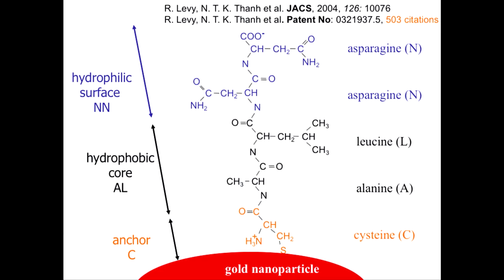So fundamentally, as you're guessing, why the change between red and blue is fundamental in terms of the stabilization of the nanoparticle. So we have two mechanisms. One is steric stabilization. That means here is the peptide of amino acids, and we have egg white, which is protein, which is much longer, so they provide the steric stabilization. And at the same time, sometimes if citrate is negatively charged, you have electrostatic stabilization, so they repel each other. So gold nanoparticles are really separate apart. They don't come together, so they don't aggregate.